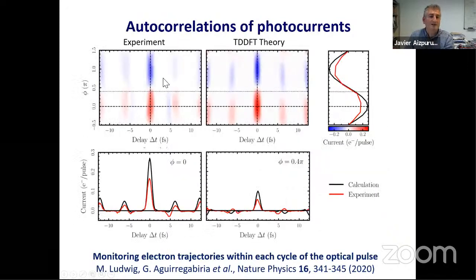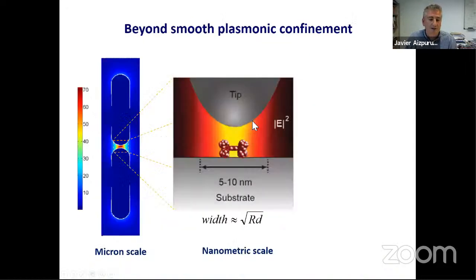Experimentally, they can come with two pulses, and measure autocorrelations of the photocurrents with time delay. And we see that our time-dependent density functional theory reproduces these experiments here. In this cross-section, you can see that the current burst, the photo-induced currents, last less than 1 femtosecond. So this is ultra-fast photocurrents, photo-emitted currents, that we can identify and describe within this dynamics study of the electrons. And this is the plasmonic response of the cavity, which is helping to extract the electrons. And once they are extracted, they follow just the potential of the optics, right?